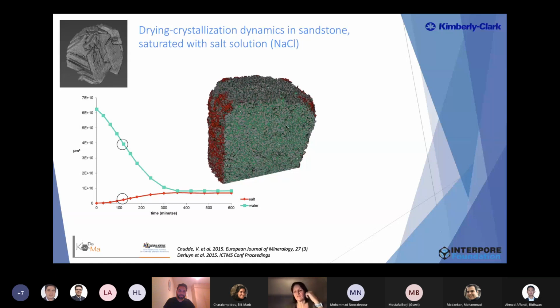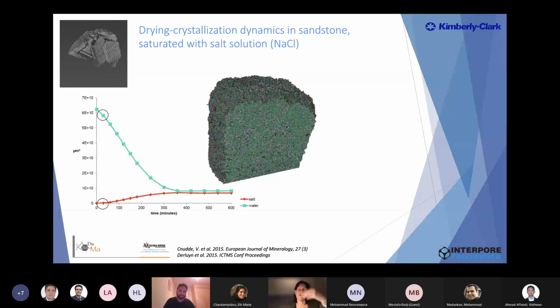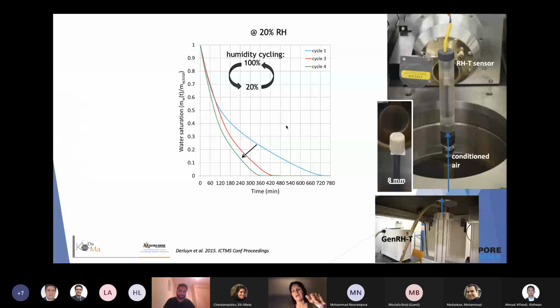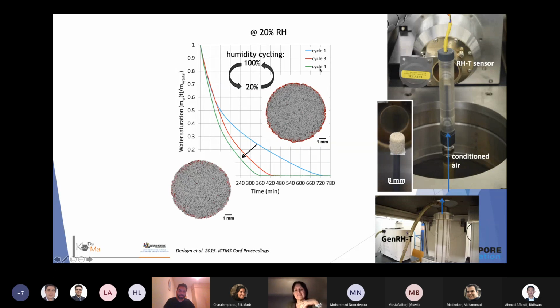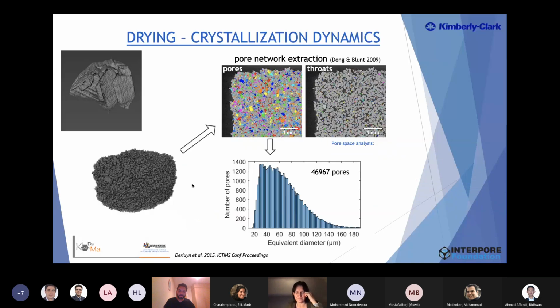Because it's a non-destructive technique, we can monitor what happens if we re-wet our sample, and if we dry it again. So you have the possibility to do cycles of changing humidity and temperature. This allows us to see that if you re-wet and dry again, the salt does not precipitate at the same location, but starts to migrate inside your material, which is logical, but it's important input for models simulating salt crystallization, and a good validation tool for that.